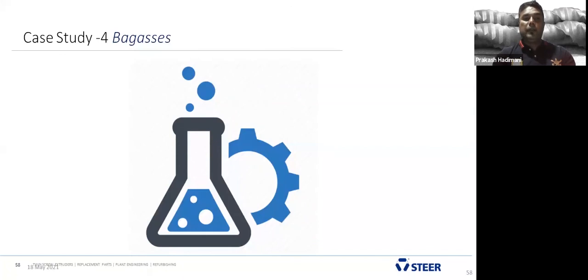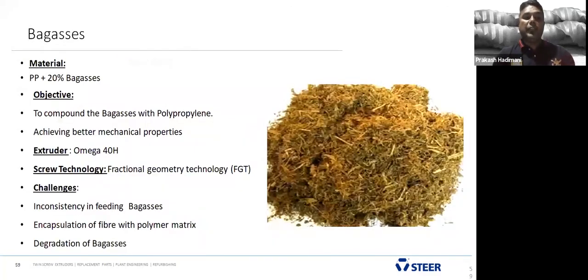And the fourth case study, we are going for bagasse. Bagasse, we have added 20% of bagasse, using Omega 40H extruder. Here we had a lot of challenges: inconsistency of feeding bagasse because it was so wet and there are no uniform fibers in the bagasse. And degradation of bagasse is again the biggest challenge.